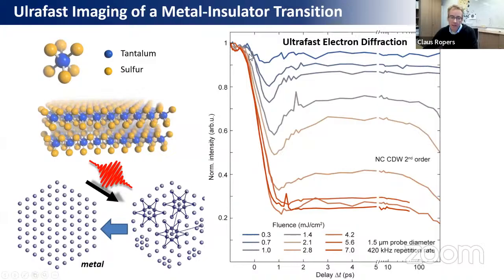Here's some exemplary data. Basically, this is the normalized intensity, normalized to before the optical excitation, of these superstructure diffraction peaks for different fluences. I don't want to go into too much detail here. Essentially, what you see is a very fast quench of the structure, so a transition towards this phase within the first picosecond, and then depending on the fluence, when you're above threshold, you completely quench this structure.